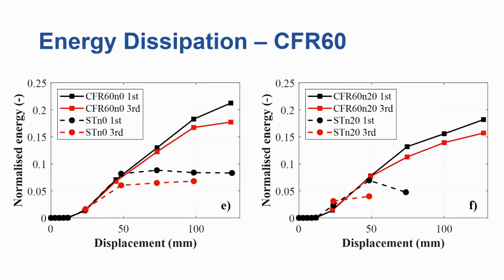And really, we don't see much of a difference. When you look at the normalized energy dissipation, we don't see much of a difference between the concrete filled specimens. However, as the axial load level increases, we see a reduction in the normalized energy dissipation.